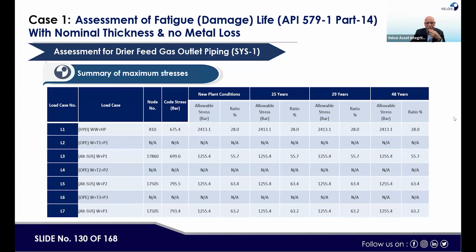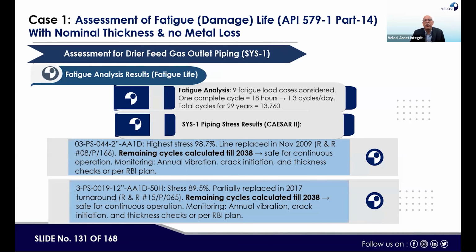So the first thing is stress analysis by Caesar 2, which shows the stress ratio, and high stress points can be seen, and then focus can be given to those points. Those points may become a weak point or at some stage may fail. So under fatigue analysis, then we went life-wise. For fatigue analysis, 9 fatigue load cases were considered, 1 complete cycle is 18 hours, 1.3 cycles a day, total number of cycles for 29 years 13,760. So here remaining cycles were left till 2038, and in the other case the remaining cycles are still balanced.